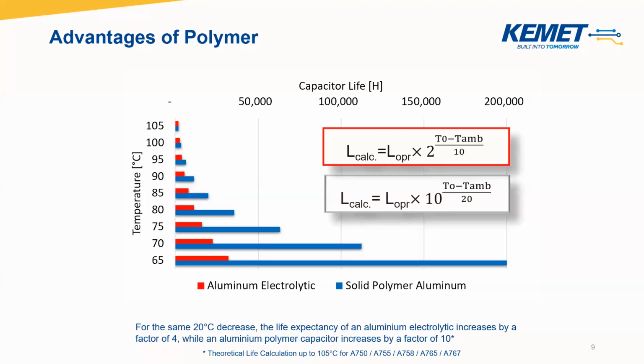Speaking of life, for the solid polymer aluminum, for every 20 degrees C drop in temperature, the life increases by a factor of 10, compared to the wet electrolyte capacitors, where for every 20 degrees C drop in temperature, their life only increases by a factor of 4. Now, currently, this is only true up to 105C. KEMET is currently investigating using our 125C parts at 105C to see what kind of benefits there are.